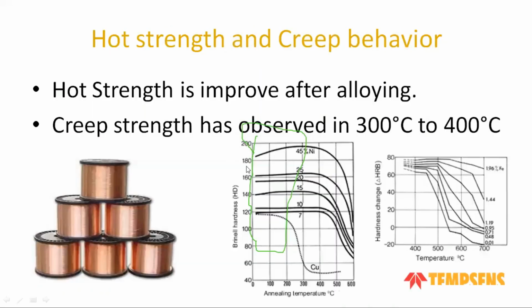You can see that hot strength plays an important role. In the hardness measurement, hardness has been reduced with the increase in temperature, while with the improvement in nickel percentage, the Brinell hardness is also improved. These are very important things to observe. The creep strength is also improved, observed between 300 and 400 degrees Celsius, which is a very good amount of creep strength. If we change the hardness parameter, we can observe this also above 500 degrees Celsius.